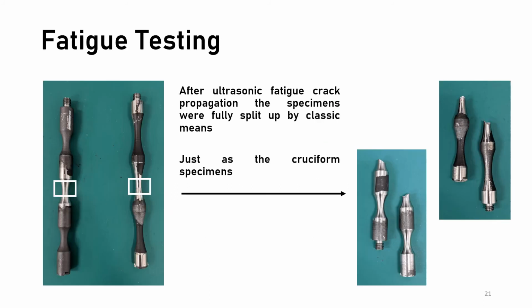Now, just as cruciform specimens, tension-torsion specimens, after reaching a certain size of fatigue fracture, lose resonance and require to be fully split up by classical means. This is the only way to have access to the fatigue fracture surface.